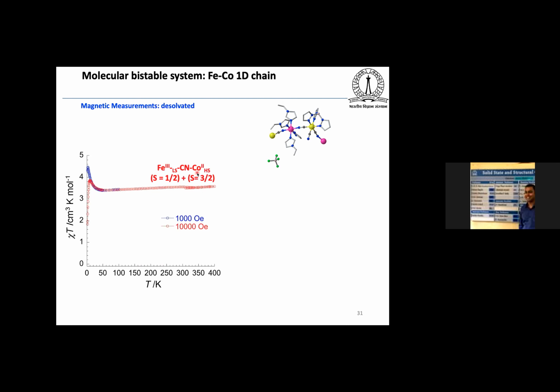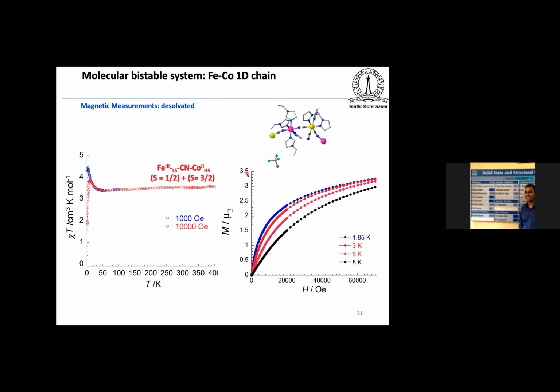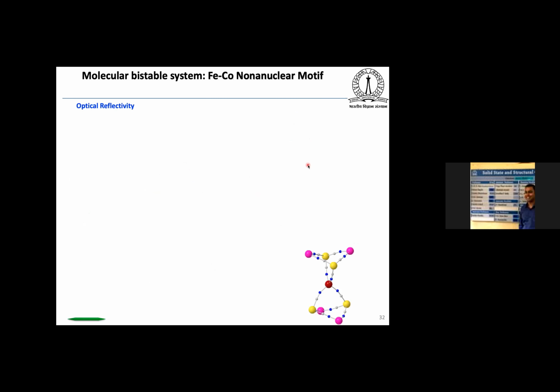And you can see this matches very well with iron 2, iron 3 in the low spin state, S = 1/2 system, and cobalt 2 in the high spin state, S = 3/2 system. And also the M/H plot at low temperature is suggesting the paramagnetic ground state of this system.